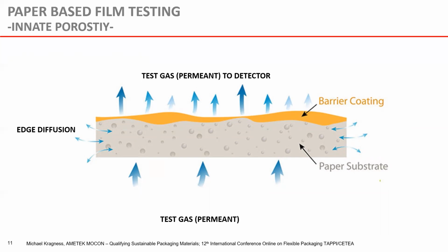The thing with having paper as a substrate is you get edge diffusion at the edges. Edge diffusion is essentially where the atmosphere can come into the structure and influence your driving force. So if you were at 100% oxygen on one side, it goes into the structure and you can lose some of that 100% oxygen out through the edges, because diffusion is random. The molecules want to move in every direction, so if they can move through the edges, they will. And it's also twofold, because the atmosphere can also move in through the edges, which can also change your driving force. If you're running a water vapor test in a very highly humidified environment, that moisture can move into your structure and cause your water vapor transmission rate to increase, because the edges were open or you did not seal the edges and edge diffusion took place.